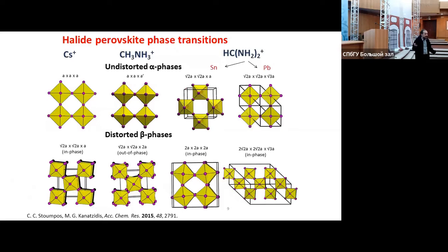So halide perovskites, as you know, undergo structural phase transitions, depending on temperature or pressure or even composition, so you can fine-tune them. And you usually refer to those as alpha phases, meaning that we have the highest possible symmetry, normally cubic symmetry, when the cation is cesium, a sphere. Or if we have less symmetrical cations, we have pseudo-tetragonal or pseudo-orthorhombic configurations, depending on what sits on the A site. These phase transitions differ with temperature for each of the three cations I mentioned at the beginning, and can be in phase, where all the octahedra move in the same direction, or out of phase, where every layer of the perovskite shifts in different directions. This is called an out of phase situation.